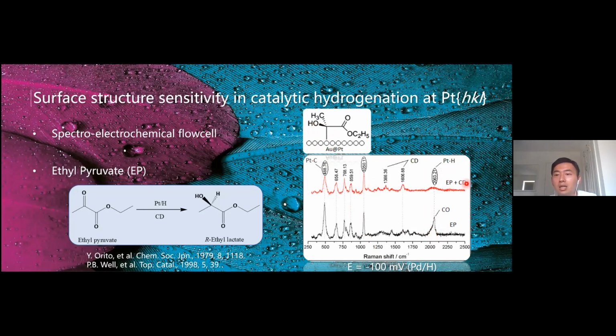Then a type of modifier, cinchonidine, was added to the solution. We could see that we could reduce the amount of CO formed and increase the final product yield. This type of intermediate is called the half hydrogenated state of EP on a rough platinum surface, discovered in the last century. So by this point, we don't know what kind of surface is actually active for the reaction and what is contributing to the CO formation.